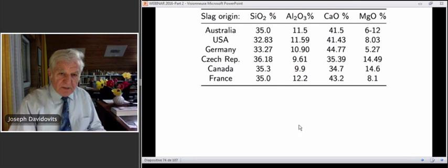If you take slag and just look at the oxide composition, depending on the origin, you have different amounts of the elements. What is striking is that a lot of people are only looking at CaO, because for them this analysis gives the amount of CaO. They confuse the CaO, which is just an oxide analysis, with quicklime or lime. For them, slag is in fact a type of lime, Ca(OH)2 or CaO, that will harden because of alkali activation.